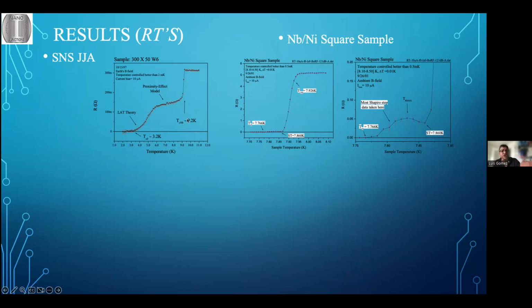And then the transition occurs right at 9.2, but in this case it's about 7.9 when I can see that the transition occurs. Then it goes very sharply, about 7.8, we almost reach zero. But I'm not sure if you can notice here, this is not quite zero. It may be below 7.76, and I'd like you to see the accuracy of each one of these measurements. I have millikelvin control and stability for each one of these measurements, even from this system and that system.